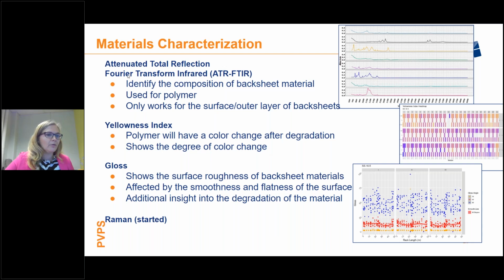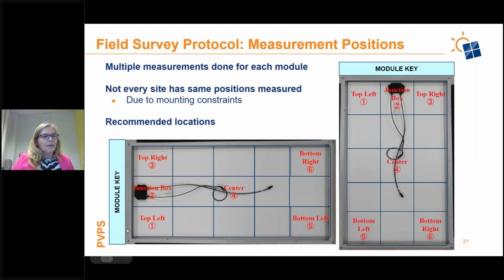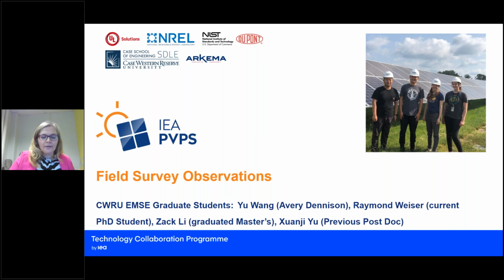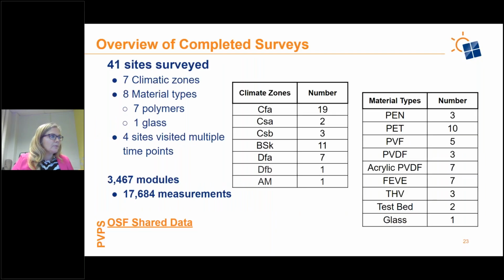So we went out and we used ATR-FTIR to identify backsheet type, yellowness index, gloss, and then we started with handheld Raman as well. And then we decided where to measure on the backside of each of these modules for time and to maximize the number of measurements that we could also take. And then I'll walk through some observations.